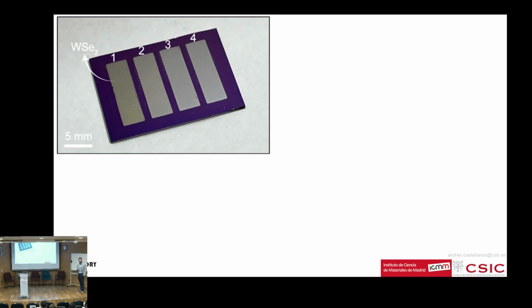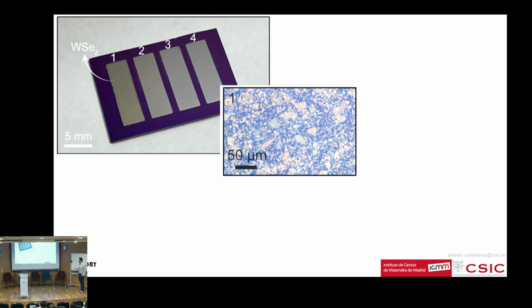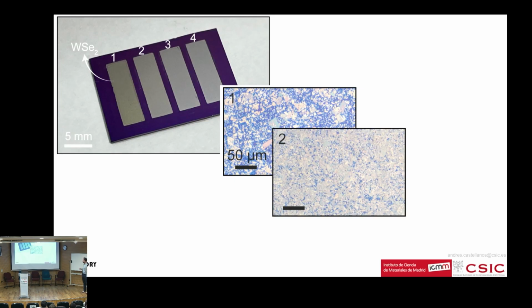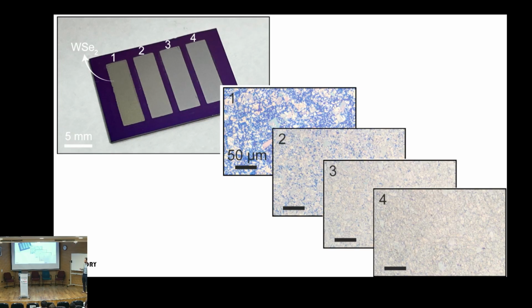And actually, we can. So we do this thermal release transfer sequentially. In this case, we have 1 transfer of tungsten diselenide, 2 transfers, 3 transfers, 4 transfers. And you can see in the optical microscope that if you do only 1 transfer, all these bluish parts are the bare substrate, the silicon oxide that is uncovered, okay? So you see the blue part, no? So you see some gaps. You do 2 transfers, then you cover more, 3 transfers, 4 transfers, you get very good percolation, okay?